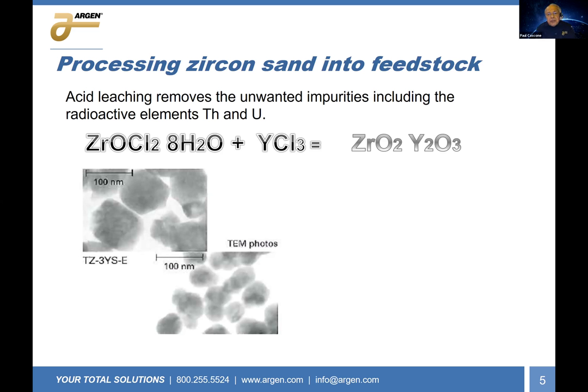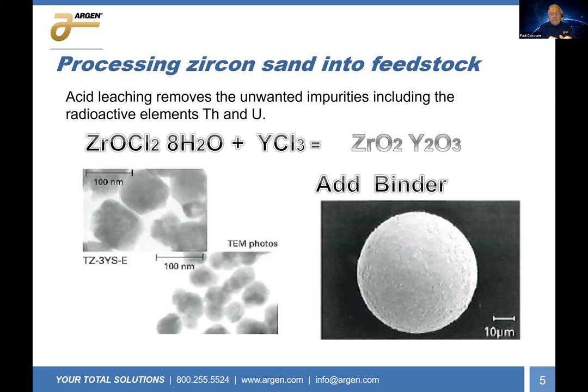So let's just continue for now, and we're going to take this material and spray dry it, which means we get rid of the water, the chlorine goes off as a gas, and we wind up with the oxides. And along with that, we add a binder. When we spray dry it, it comes out as all these beautiful little spherical particles. And again, they're very small, only 10 microns in diameter. So now the binder is intimately involved with the crystallites.